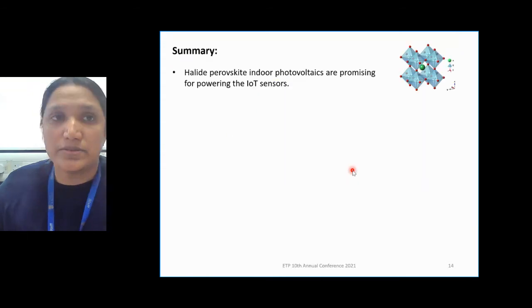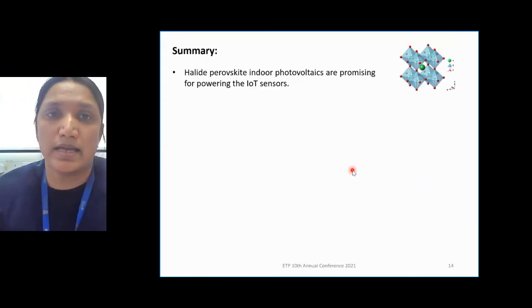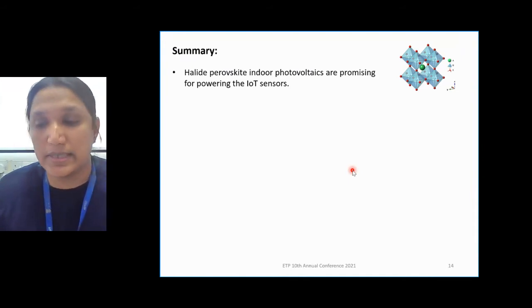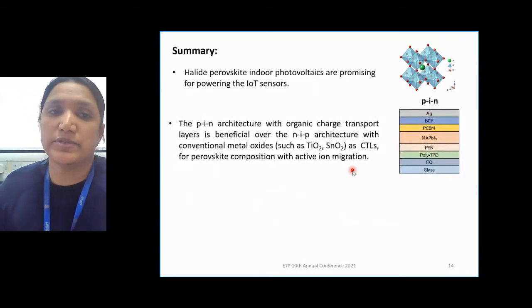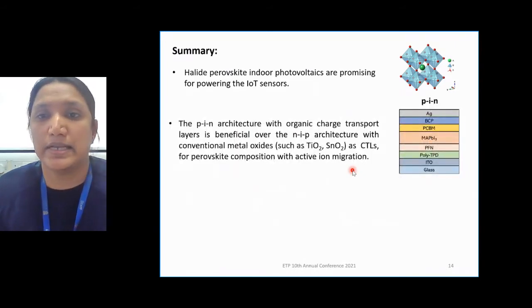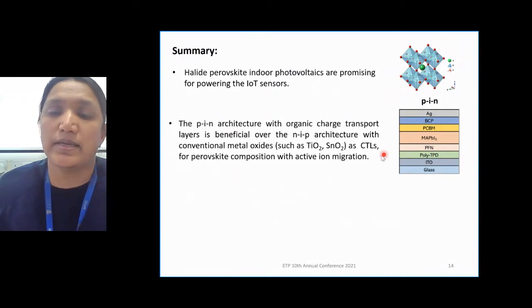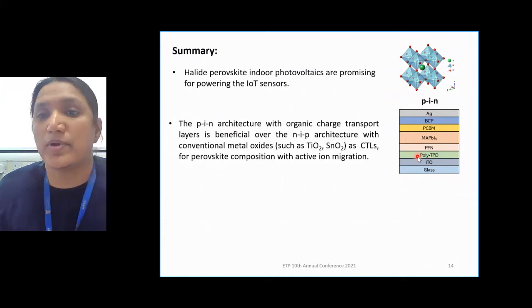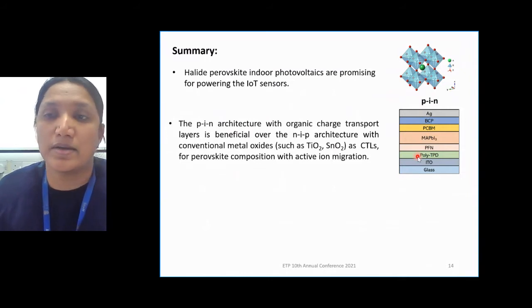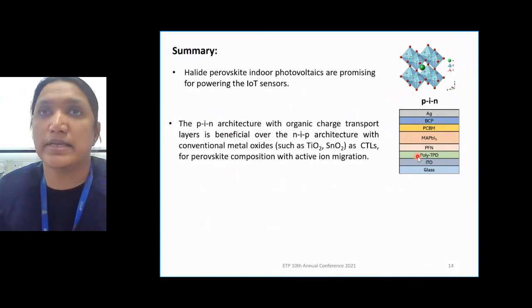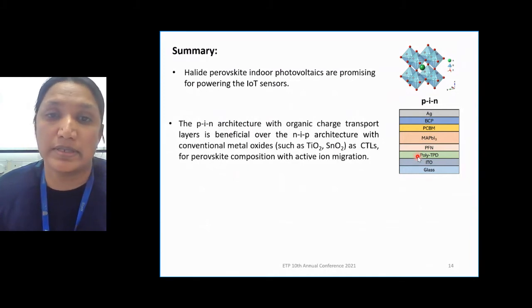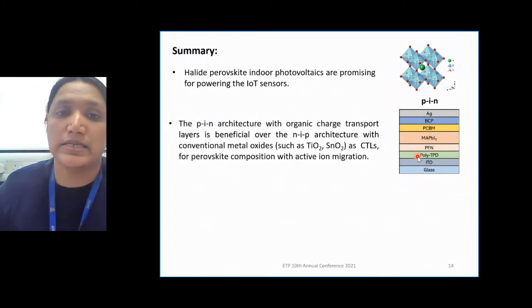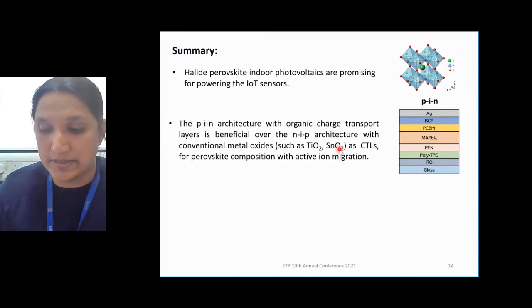So to summarize, our study has shown that halide perovskite indoor photovoltaics are promising for powering Internet of Things wireless sensors. And between the two device architectures, we have seen that the PIN device structure with the organic charge transport layers is promising because of its high power conversion efficiency and less hysteresis effect compared to the conventional metal oxide based NIP devices. We have repeated these devices with TiO2 as well and saw the same observation.